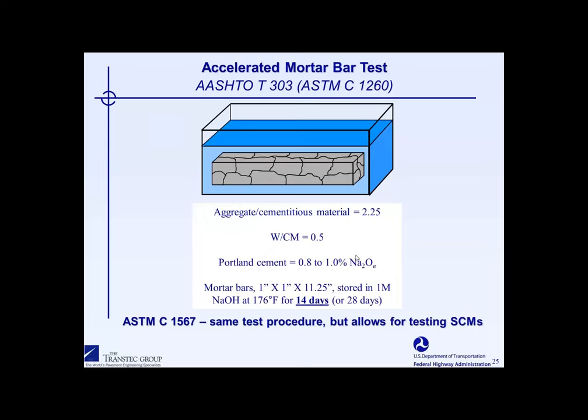The test is most commonly run for 14 days. That's what is recommended in the AASHTO protocol that's discussed at a later date, and also a little bit in this presentation as well. Some agencies, owners and specifiers have suggested that the test should be conducted for 28 days instead of 14 days, and we'll discuss that in a little more detail.